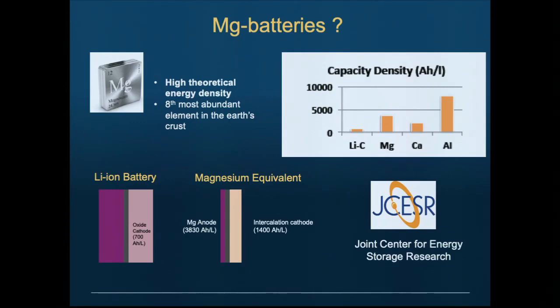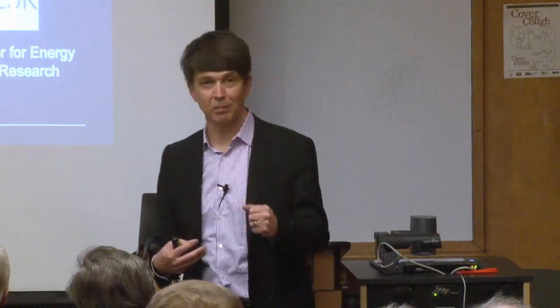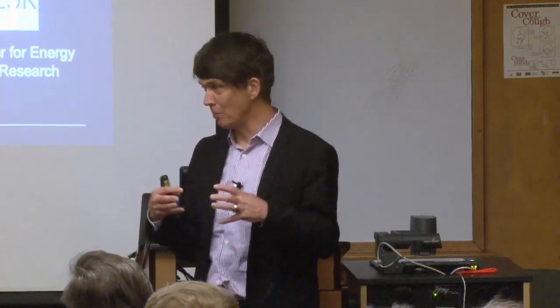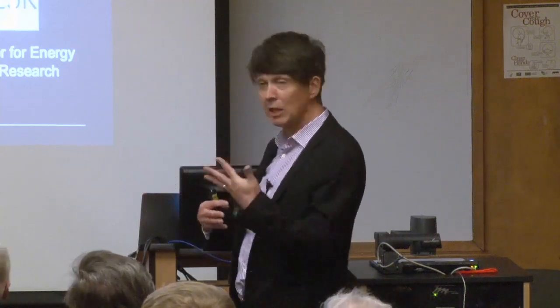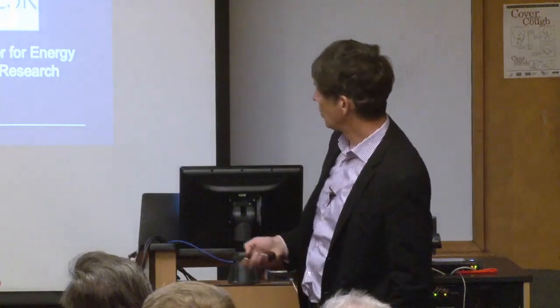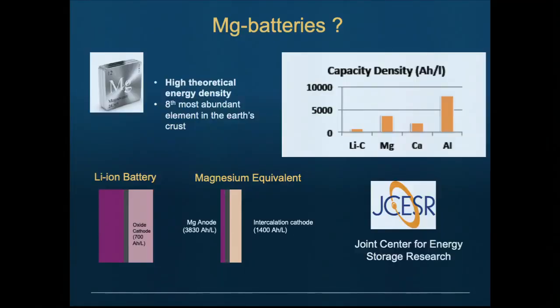A good cocktail party story is that the density of magnesium ions in magnesium oxide is higher than in magnesium metal, right? It's such a densely bonded material that there are almost no point defects, so you can get nothing through. So the magnesium anode is extremely passivated. But it has enormous charge density, right? If I take an equivalent lithium anode and now take the magnesium equivalent in terms of the amount of charge, you see it gets super thin. So in principle, in terms of energy by volume, which is, by the way, the criterion that most applications care about, not energy by weight, magnesium anodes would be enormous.